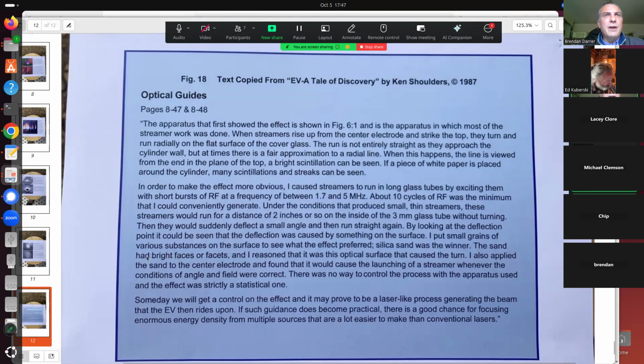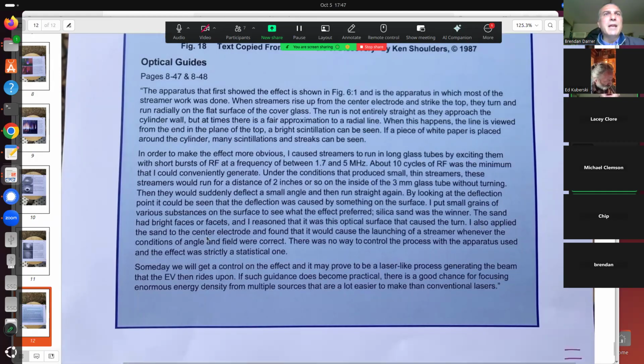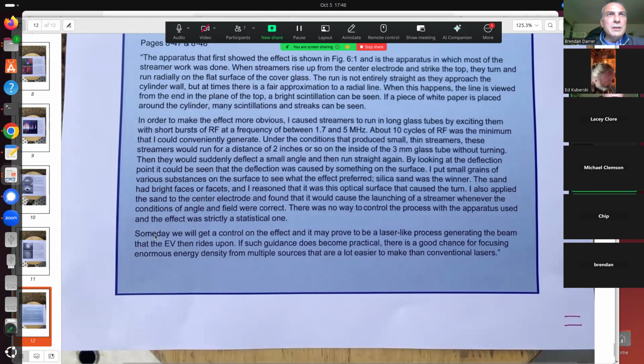The sand had bright faces or facets, and I reasoned that it was this optical surface that caused the turn. I also applied the sand to the center electrode and found that it would cause the launching of a streamer whenever the conditions of angle and field were correct. There was no way to control the process with the apparatus used, and the effect was strictly a statistical one. Someday we will get a control on the effect, and it may prove to be a laser-like process, generating the beam that the EV then rides upon.